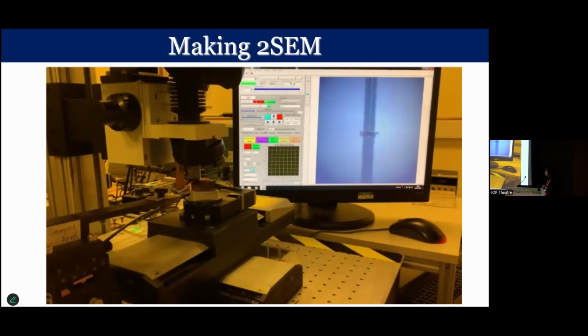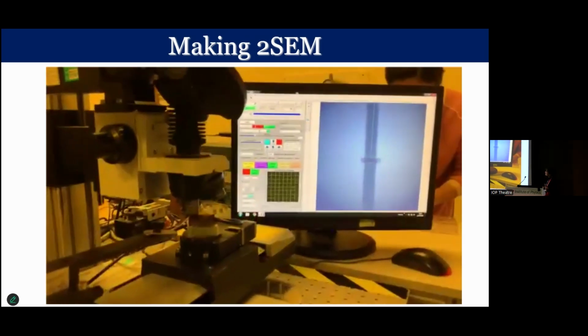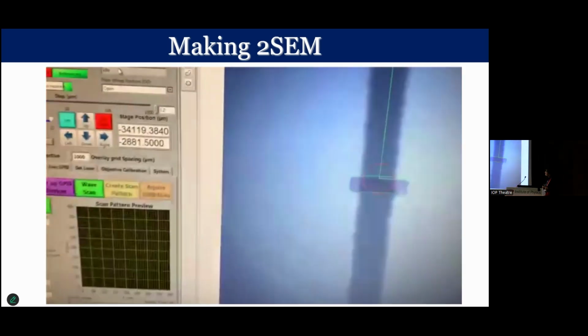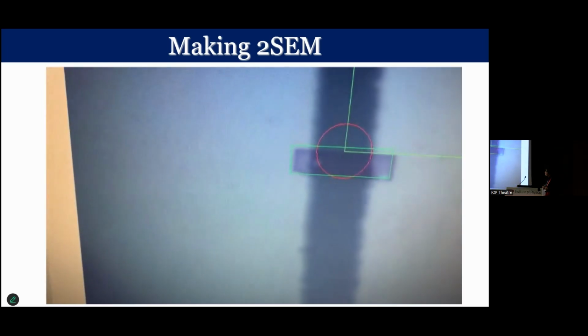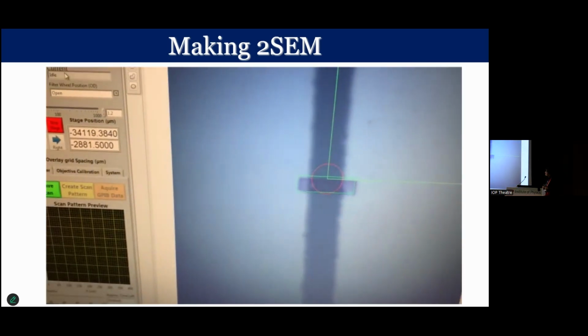We then bake the sample at 180 degrees Celsius for about 10 minutes to improve adhesion, and then perform solvent cleaning and anneal at 300 degrees Celsius to remove any PMMA and impurities on the graphene surface.